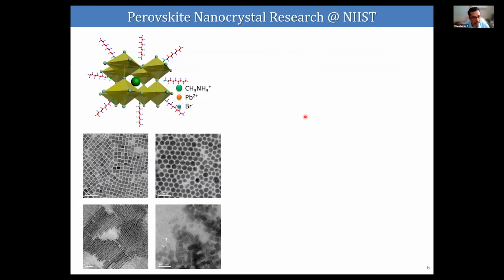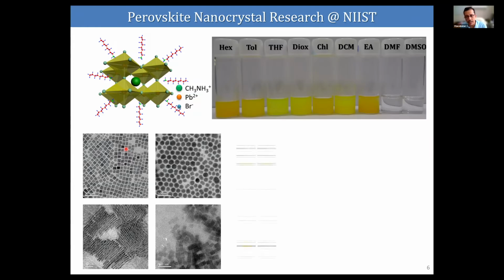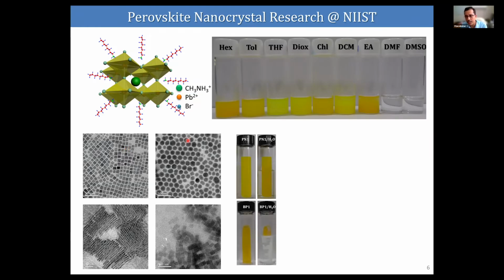And we developed several perovskite nanocrystals, mostly with methylammonium and formamidinium cations, organic cations, and we made several shapes and materials with different shapes and aspect ratios, as you can see here. And they show excellent stability in most organic solvents, except in highly polar solvents like DMF and DMSO, and they show very good stability even if we dip them in water, compared to the 3D perovskite.